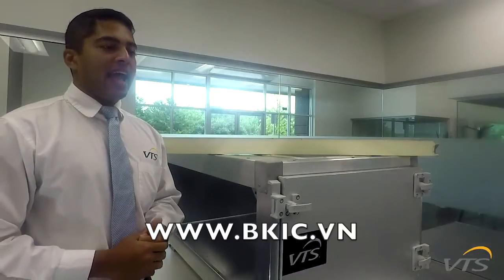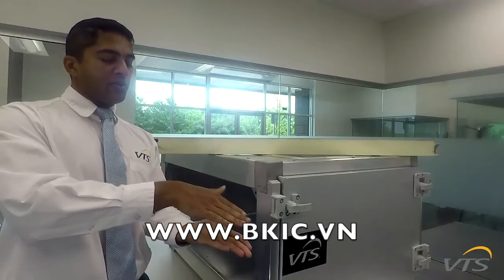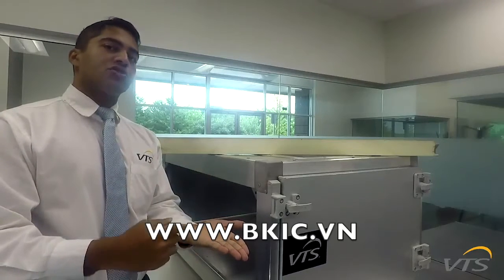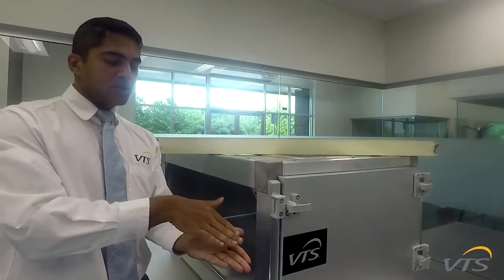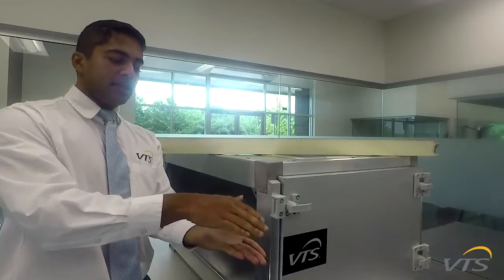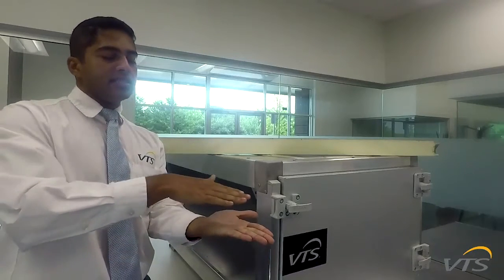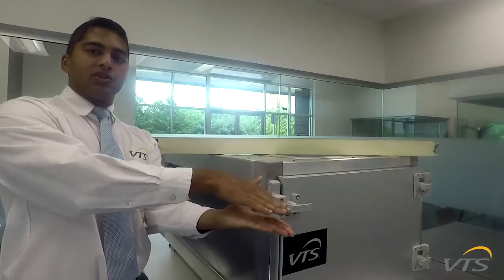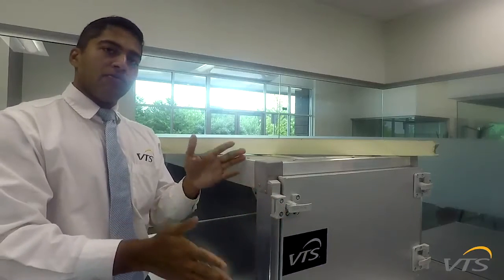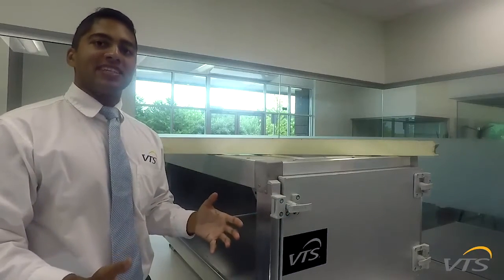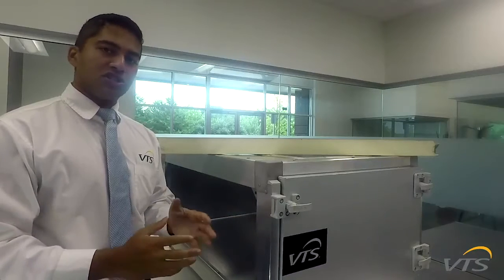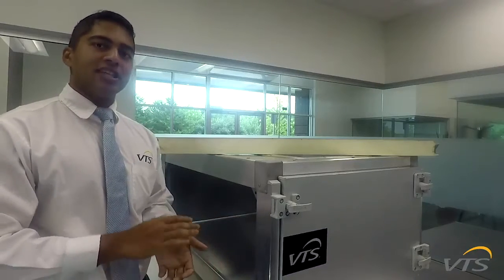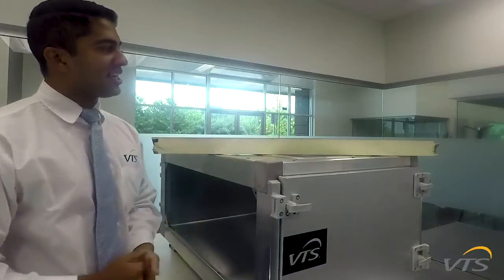We apply a thin layer of the polyurethane foam, and as it's going down the conveyor, we add in heat at certain stages. So we do a temperature-controlled process. This minimizes any bubble sizes, and when you think about it, as it's going down like a conveyor, both the sides are completely open and ventilated to the air. So that's how we ensure proper ventilation and then uniform distribution of the insulation throughout.